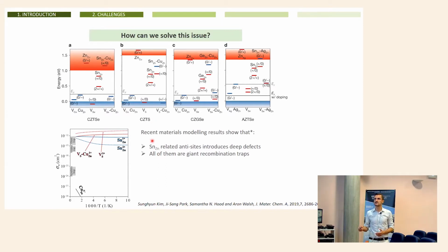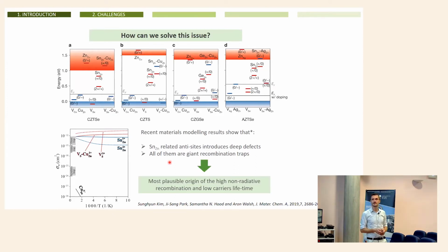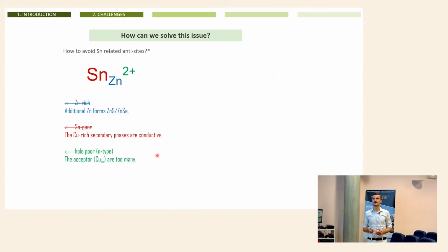And all the tin-related defects used to be giant recombination traps and can be the origin of this VOC deficit. So right now we are investigating these possible tin on zinc defects to improve our kesterite. But how to try to reduce the concentration of this defect or avoid the presence of these defects? One possibility is to go towards zinc-rich conditions.